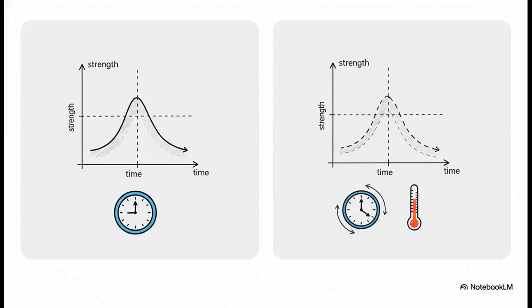Okay, so if our T6 alloy failed, it means the recipe went wrong in that final aging step, and that leaves us with two main suspects. Suspect number one is underaging. This is what happens if you don't cook it long enough. You'll get some good precipitates, sure, but you haven't hit that peak strength yet. There's still potential left on the table. But then there's the second, and I'd say more sinister suspect, overaging. This is what happens if you go too long or the temperature is too high. You blow right past the peak, and all those strong, coherent particles transform into large, weak, incoherent ones. The strength you worked so hard to build literally starts to melt away.